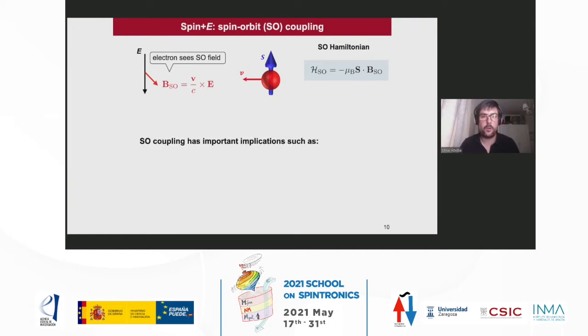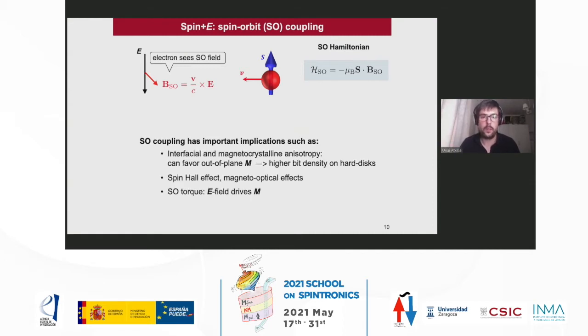Spin orbit coupling, which you have already heard about during this school, has important implications, such as magnetocrystalline anisotropy that can favor out-of-plane magnetization. This is very good for higher bit density on hard disks.